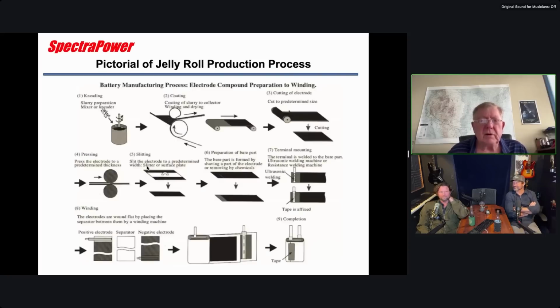This is a pictorial. So this is just mixing the slurry, and you coat it. You use either a reverse roll coater, it's called, or a slot die. You cut it to the size you want if you're stacking. You roll press it through these calenders, and then you slit to the width and exact size you want in the cell. This preparation of bare part is where you have to clear an area off of the coating to get to the metal so you can tab to it or weld to it using an ultrasonic welder.